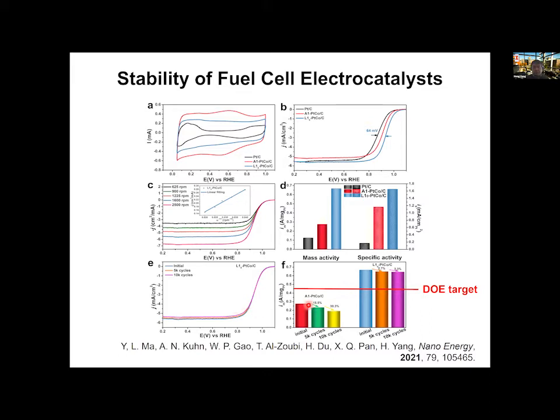One of the encouraging measurements for the fuel cell catalyst performance is the durability. And the last panel of this fuel cell test gives us some clue on that. If you have the intermetallic structure, the durability is maintained quite well. The activity after 10,000 cycles has only dropped by 3.3%. Unfortunately, in further testing with longer cycles, the durability does not maintain as well as this, so we're still trying to figure out the exact reason for that. If you look at the non-intermetallic larger system, it can actually drop by 30% under the same performance chart.